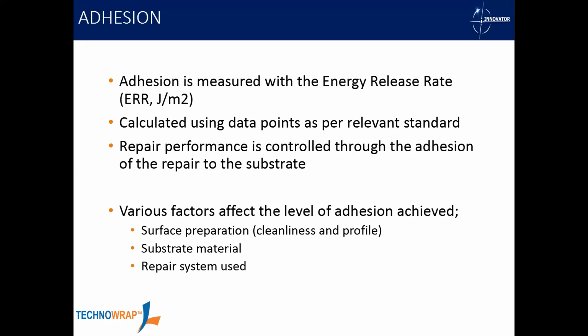So back to adhesion. As I said, this really is the most important thing when it comes to composite repairs. If we don't bond, you don't transfer load into the composite, therefore the composite isn't actually doing anything, it's not fixing the problem. And the way we quantify adhesion is with an energy release rate. This is a fracture mechanics technique that we use to basically say what load can you transfer through a bond line without failure. And the way we do this is we calculate it using pressure. So we have a set pipe with various size defects and apply pressure to failure. We can then get the data points and then extrapolate for different scenarios.